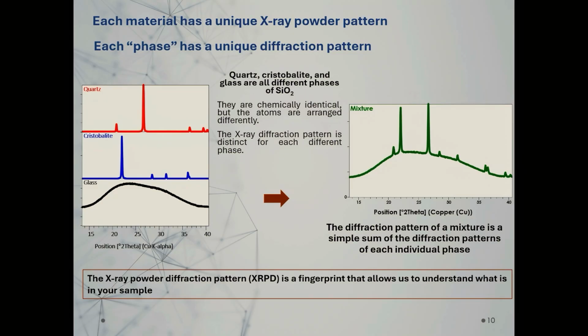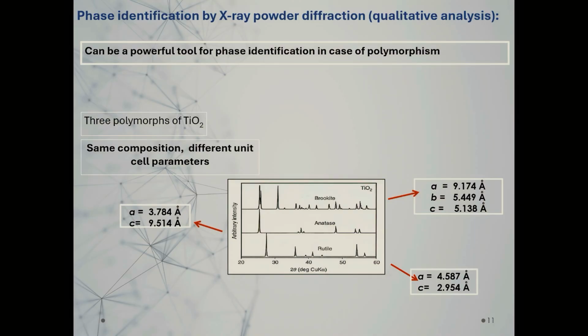So it's a way to say that each material has its own fingerprint that allows us to understand what is inside your sample. Phase identification can also be a really powerful tool to identify polymorphs. Here are reported the 3 polymorphs of titanium oxide: brookite, anatase, and rutile, and the corresponding cells are reported. Also, the powder diffraction patterns are quite different from each other. So if I have a sample that contains titanium oxide, by using qualitative phase analysis, I can detect which of them I have, or if I have one plus an impurity, or one plus another one.